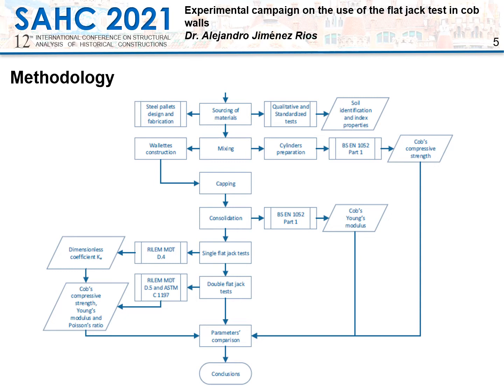The wallets were capped with a mix of cement mortar to flatten their top surface and achieve a regular load distribution, and were left in the lab, protected from wind and rain during a drying period of 3 months. The wallets were then consolidated as advised by Professor Lombillo under 2 load cycles. From the second load cycle, which resulted in a linear behavior from the wallets, cob's Young's modulus was estimated.